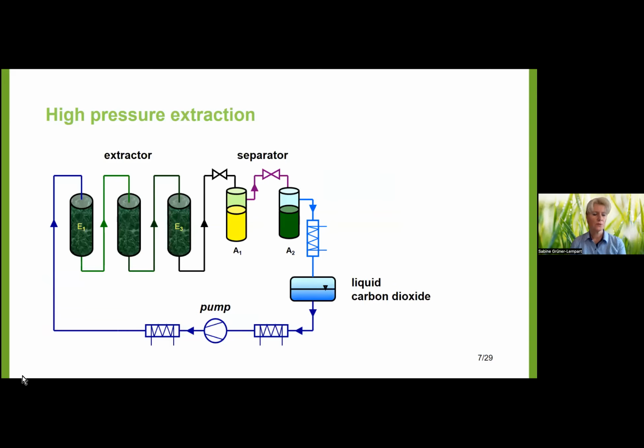I'm sure everybody of you is familiar with the high pressure extraction, therefore I go quickly through the process. You see the extractors where the plant material is placed and the liquid carbon dioxide is heated and compressed to the supercritical state so that it can flow through the plant material and dissolve all the ingredients which are soluble at the chosen extraction conditions. Then afterwards, we depressurize and get one, or in this case 2, extracts in the separators. And the carbon dioxide is recycled, so it is cooled down to the liquid state and transported back to the storage tank.